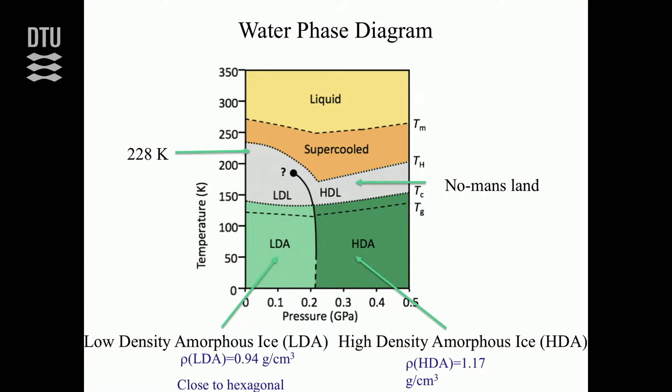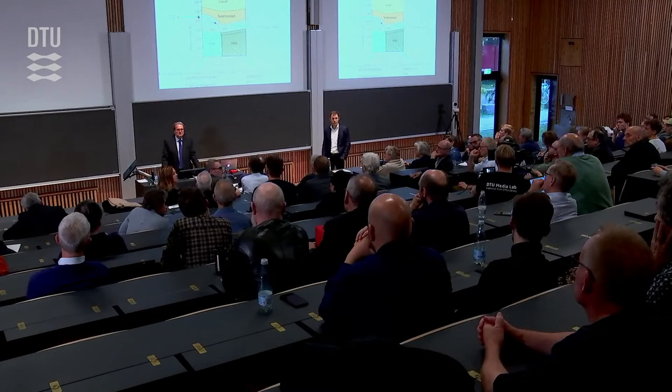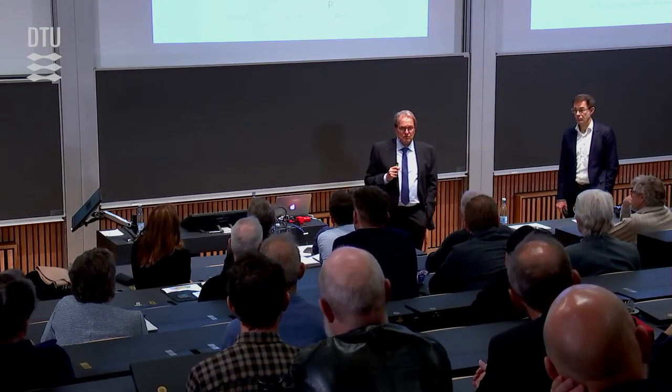Would this transition and density be larger with different isotopes, O18, deuterium? How does this diagram look for heavy water? Yes, so I can tell you that if you have D2O, you will have a shift of this Widom line of 5 degrees. We measured that, so we've done it also with D2O. And I believe we also have evidence that the critical point will move further away. So there are some aspects where these anomalous fluctuations might be more enhanced in H2O than D2O, at least at these lower temperatures,